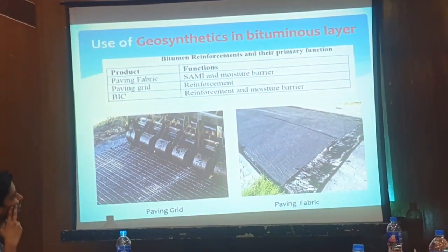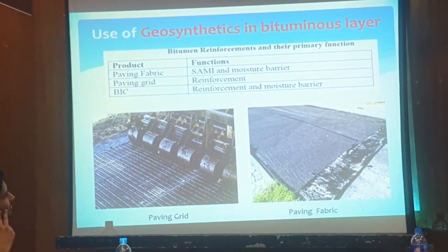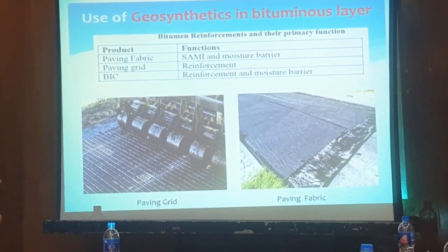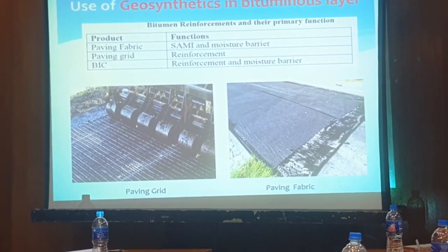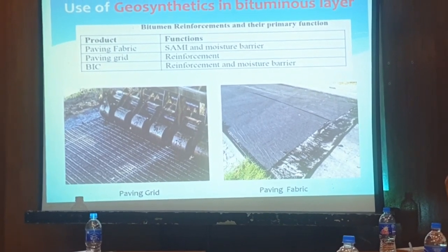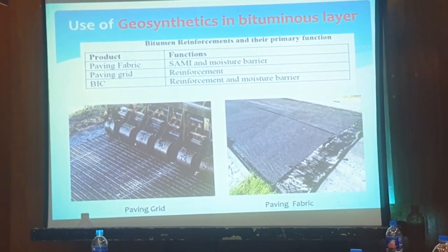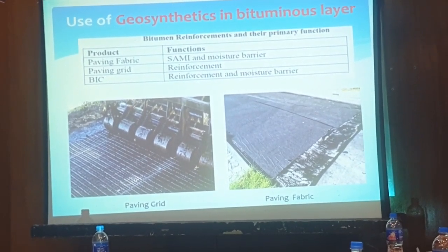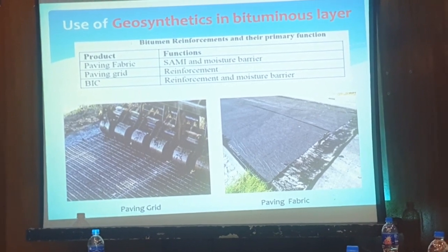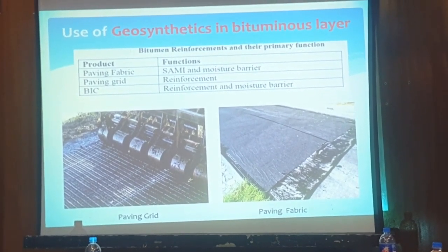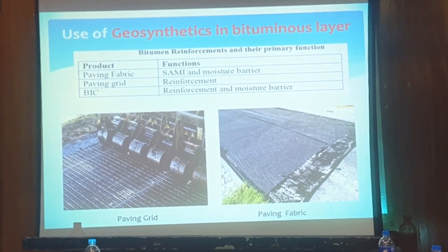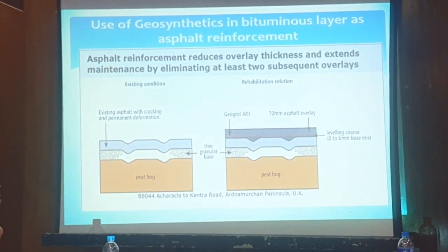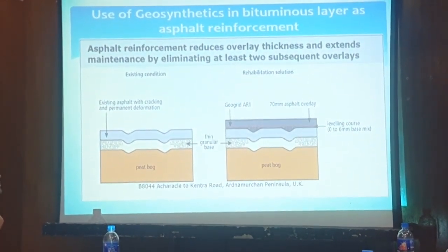And this is the asphalt reinforcement. Asphalt reinforcement between two asphaltic layers, DBM and BC, you can use it. We face the problem of construction material carrying vehicles, or wet sand, where water is being poured on the surface while heavily loaded trucks full of sand are flying over the surface. There the use of this is very ideal. This is the way it functions.